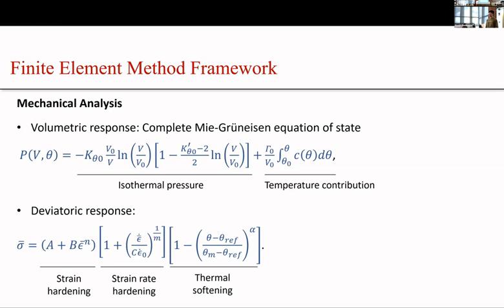Yeah, there will be some errors for sure, because like you said, they are very different material behaviors. But we know that the impedance matching technique is flawed because of those assumptions. For metals we can make those assumptions, that it's elastic, perfectly plastic, given that the shock pressure is very high. But for tungsten carbide, making that assumption is not exactly accurate. So we have to see how inaccurate the impedance matching technique and those assumptions are, and that's by comparing the simulation and that data.